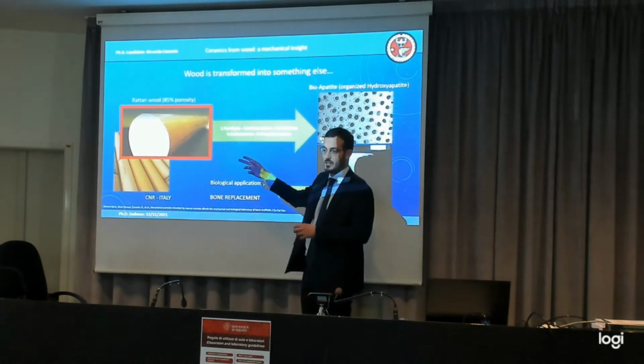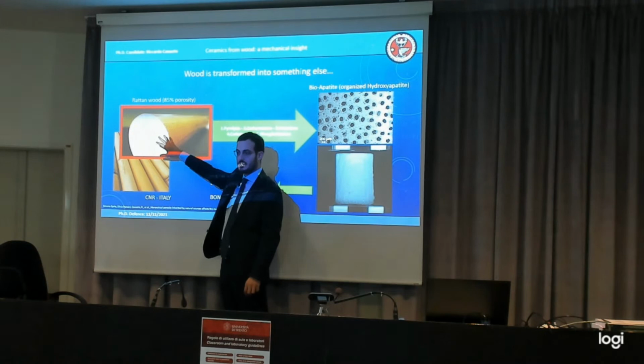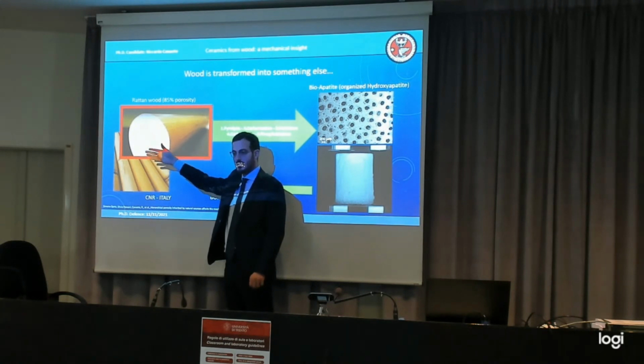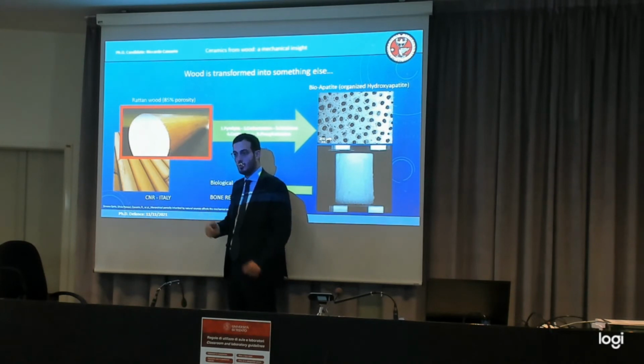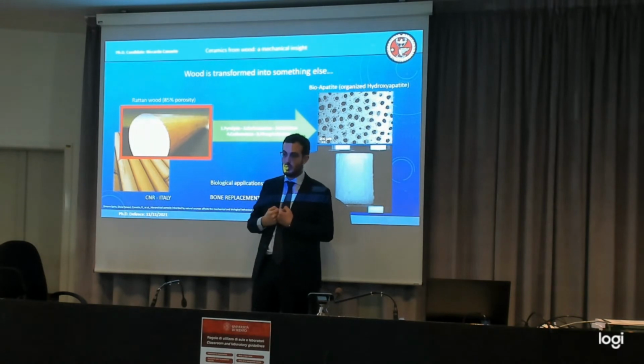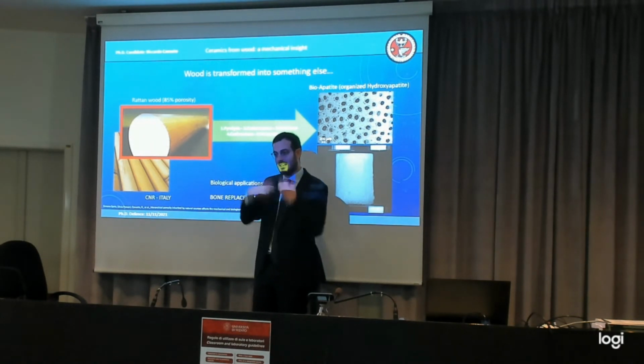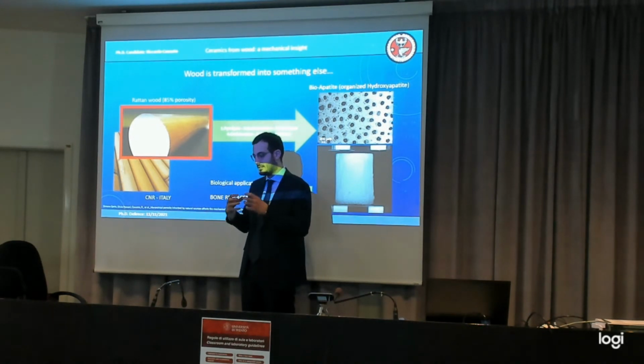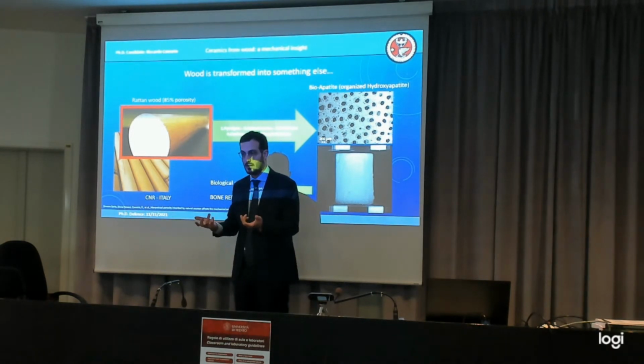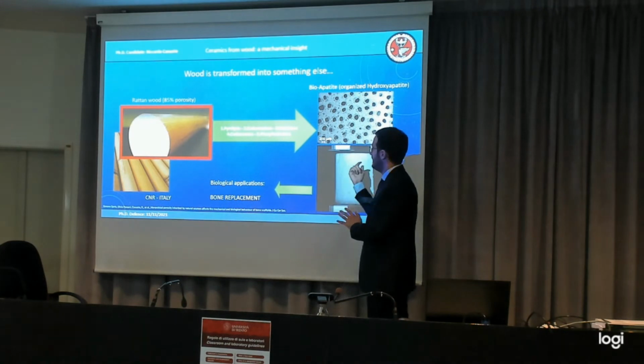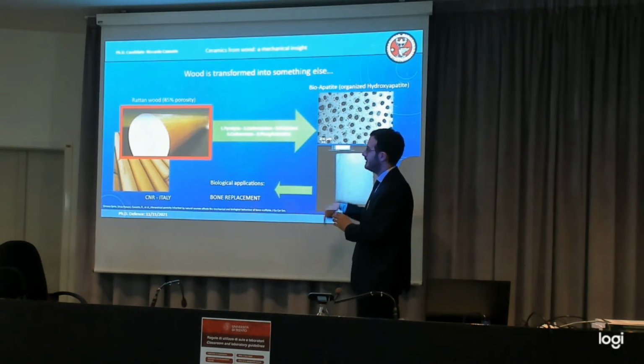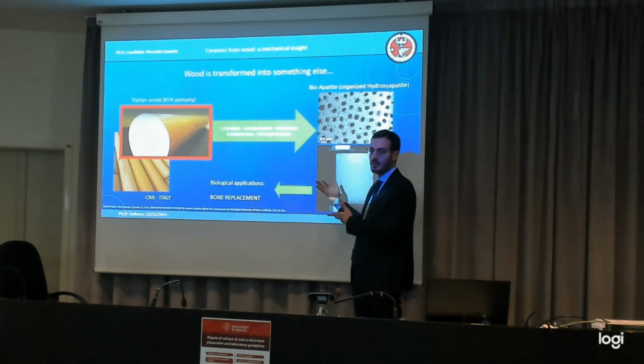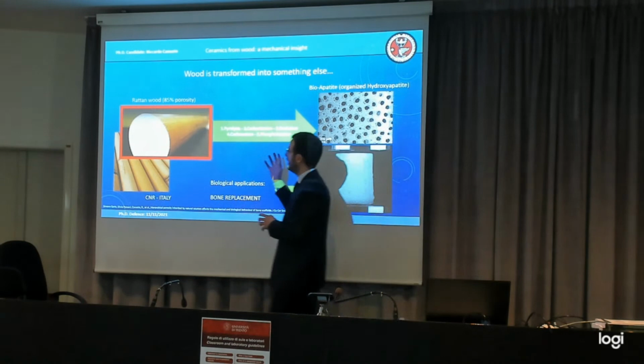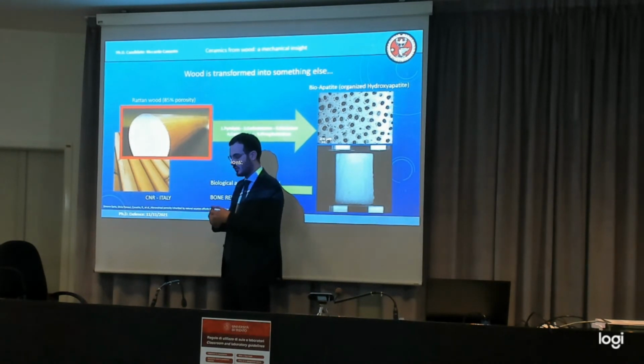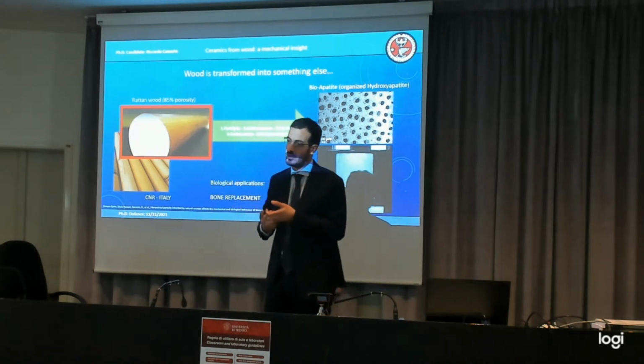Typically, this is not the way it was done, because what you typically do is that you have a structure and then you infiltrate the constituents of the hydroxyapatite, and they deposit on top of the structure, which is then burned through sintering processes and completely cancelled. And what is left is something made of hydroxyapatite, but it is built on top of something that there is no more. So the result that you obtain in stiffness and strength of the hydroxyapatite is actually performing better than normal hydroxyapatite, and that is due to the fact that by transforming it, the bonds between the molecules are stronger.